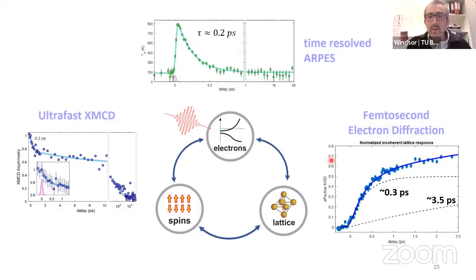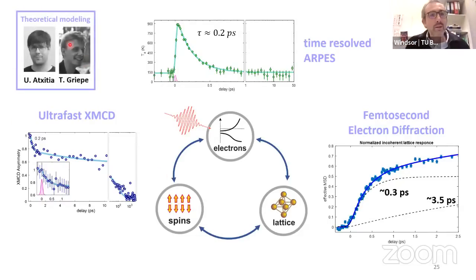So in principle, we can very easily apply a reliable model to describe energy flow between them, at least on a simple level. It turns out that this is not as simple as I would like. I'm working together with two colleagues from Madrid, Unai Atxitia and his student Theo Griepe, to use all three degrees of freedom to model energy flow in what we believe is the correct way.